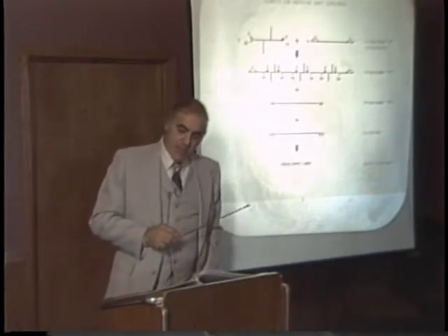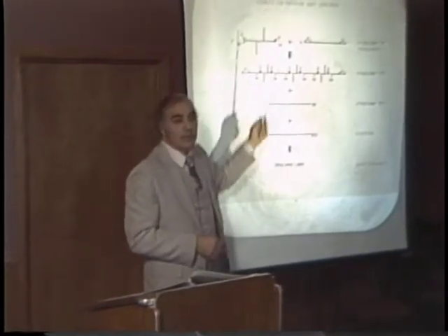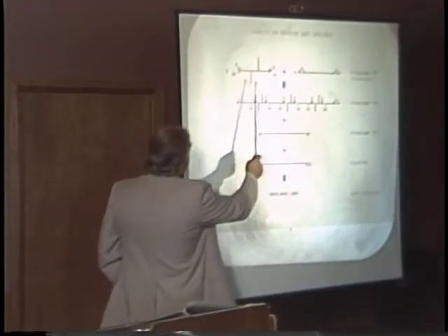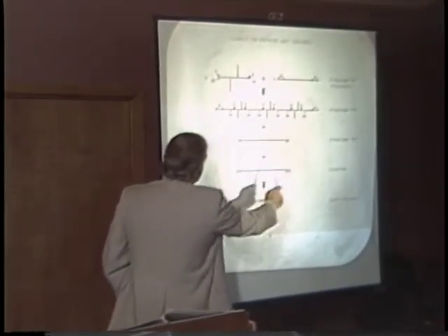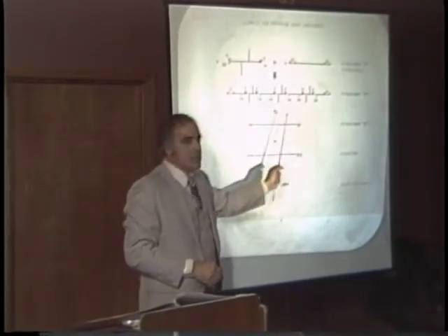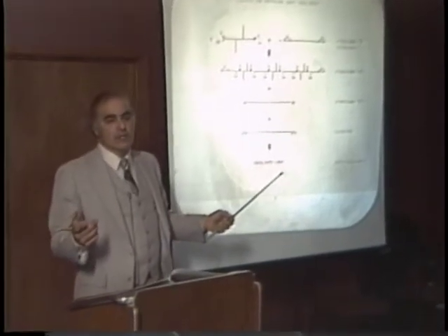So in going through the literature, we came up with a process called graft copolymerization. And what I am showing you here schematically is the way we went about doing it. We co-react a difunctional acid with a difunctional epoxide to produce an intermediate molecular weight polyester that has pendant hydroxyl functional groups. Now what we do next is that gives us one kind of prepolymer. It generally has a glass transition temperature that's too high for practical use.